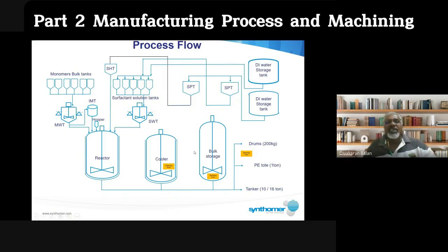So we have monomers, we have surfactant here, and we have initiator catalyst. Normally these catalysts come in powder form, so we add it directly to the reactor through this hopper. So we charge in the initial 5% of the total monomer. Normally the total monomer is around 5 to 6 metric ton. The batch is 12 metric ton, so your 5 to 6 metric ton will be monomer, and maybe 3, 4 metric ton will be water. Apart from monomer, water is another main raw material for polymer dispersion. So you must have water, monomer, surfactant, stabilizers, and initiators, catalysts. You mix all these, only then it will become polymer dispersion.